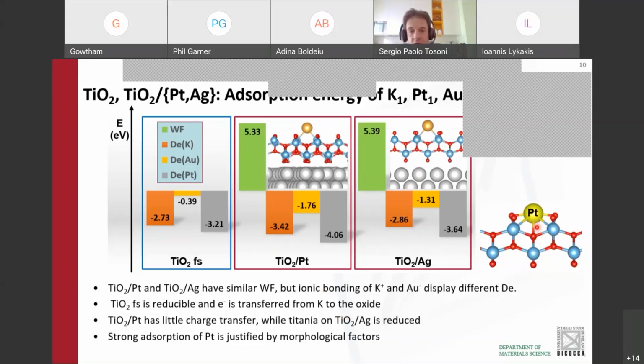And the platinum is very, very strongly bound, as you can see. More than 4 eV on TiO2 on Pt and 3.6 eV on TiO2 on Ag. This for a single atom is a large adsorption energy.